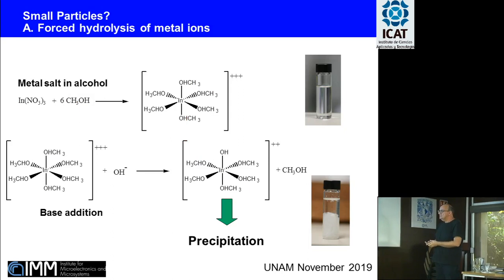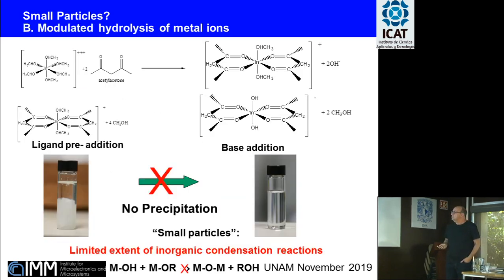So, small particles. This is the preparation procedure for our indium oxide solution, the one that we have seen before and that we use for making thin films. What happens here? If we do not use any acetylacetone, if we just put the base, we have precipitation of indium hydroxide. We put the base inside the indium nitrate solution, we have a precipitation. This is a very basic experiment, of course. But in our procedure, we put acetylacetone around the molecules, just to avoid precipitation. And when we add the base, the ammonium hydroxide, for making the Sol-Gel process, there is no more precipitation. We go from a clearly white precipitate to a completely colorless solution.